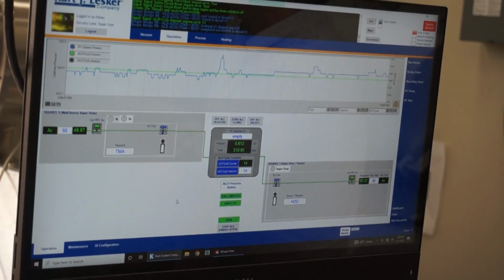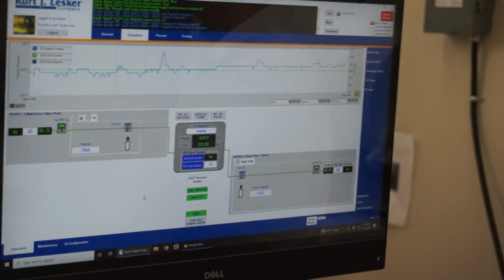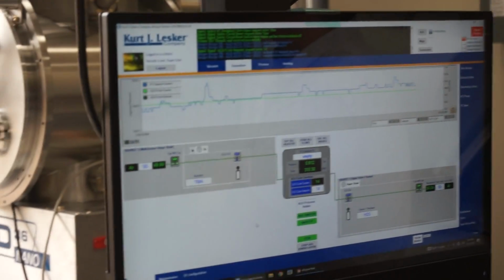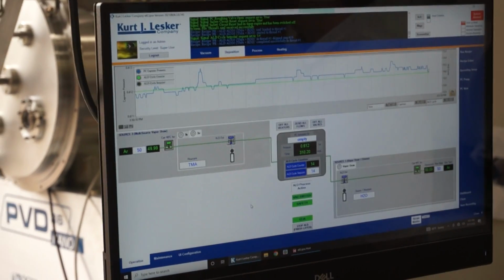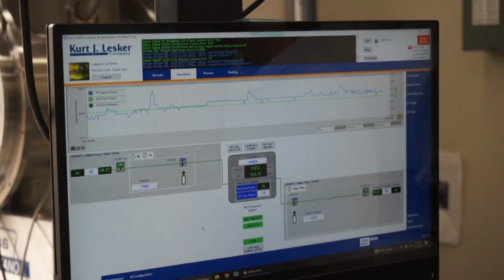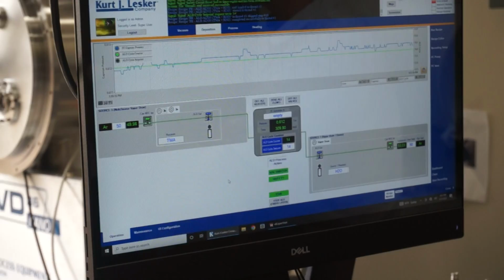Since ALD is a self-limiting reaction, meaning it only reacts to how many sites it can grab onto, anything else is wasted. So the peak height and the material you would need for a sample of a 1/2 inch versus a full 6-inch wafer is a little bit different.